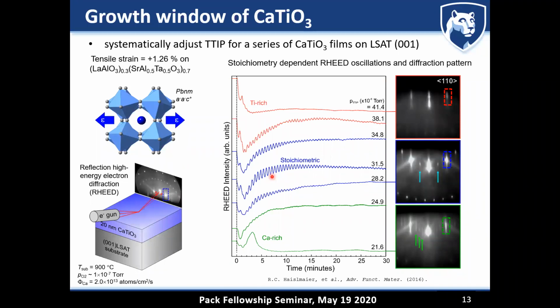And if you leave calcium titanate at 900 degrees C for some time, I think you're going to see most oxygen come out, maybe some calcium, but we haven't had any issues with this. You basically calibrate this away, because you fix your calcium flux and you're just asking yourself, how much of the titanium-containing flux do I need to get it right? It could be that we're losing some calcium on the way, but this would be really hard to track, and we actually don't care. As long as we nail stoichiometry, we're good.